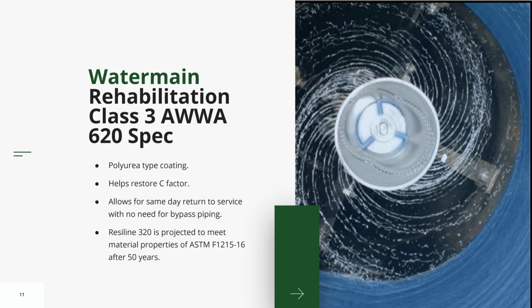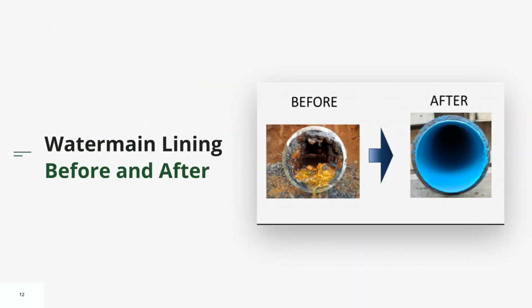Here's an example of what your water pipes can be. The water pipe on the left is an existing water pipe. That's the corrosion that I talked about on the inside. So you can imagine that the C factor, or the ability for that pipe to carry water, is quite reduced because of the corrosion between the water and the cast iron or ductile iron pipe. And on the right hand side, you've cleaned the pipe, and then you've put the polyurea on the inside of it. So you can see the increase in capacity and the longevity, and you've sealed any holes that are in the pipe.